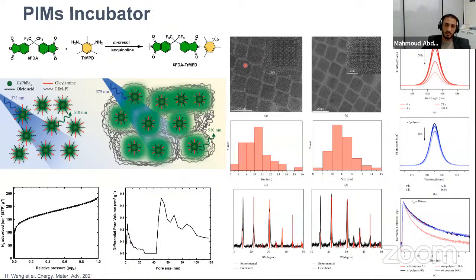This image is a high resolution TEM. You can see the blocks of the nanocrystals without the polymer and the blocks of the nanocrystals with the polymer. So almost there is no change. The polymer was integrated here and didn't affect the arrangement of these nanocrystals.